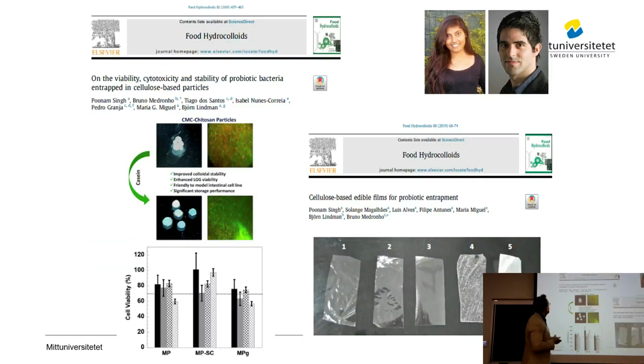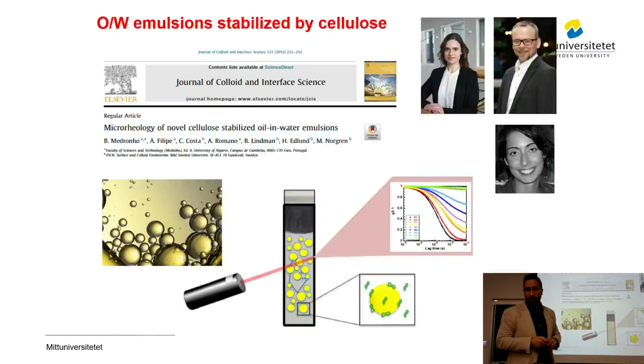We evaluated the viability, cytotoxicity, and so on, and also looked at different shapes, in this case films, not for triboelectric applications, but doping the films with bacteria, thinking about a sort of smart packaging with bacteria. It might be too stupid, but at the time we sold the idea as a kind of publication. It was very important for my PhD student. So this was also very interesting to work on a totally different area, from textile-based fibers to something more related to food applications. And as Magnus said, we explored these amphiphilic-like properties of cellulose in emulsion formation, and we